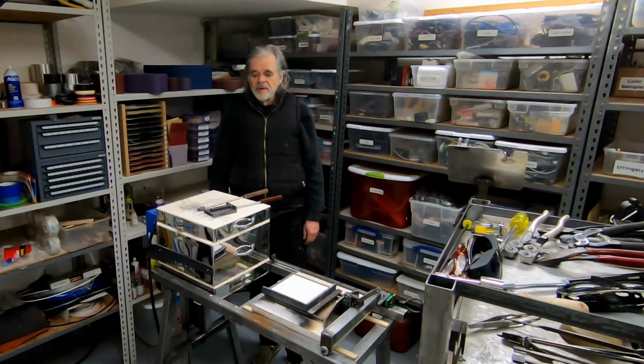One of the first experiments I tried in this kiln rig was to put a piece of graphite in, and when it came out, it was red hot, and I could obviously see that it was burning. So then I started experimenting with a variety of different ceramic materials, and the first thing I tried was regular kiln shelf ceramic, and it kind of worked, but the chips stuck to the plate if I got them too hot, and the material wasn't really that good.